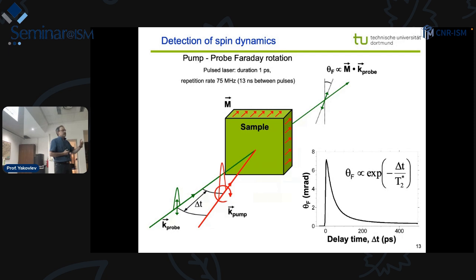I think that in this case, with the small organic materials, what people start to discuss is the so-called dynamical Rashba effect. They start, and this molecule starts to rotate. It can induce some asymmetry at certain frequency, but still, what we observe at low temperatures, when these molecules are frozen, doesn't tell us that some spin splittings are present in the crystal.